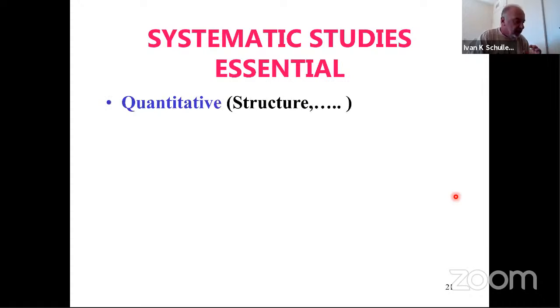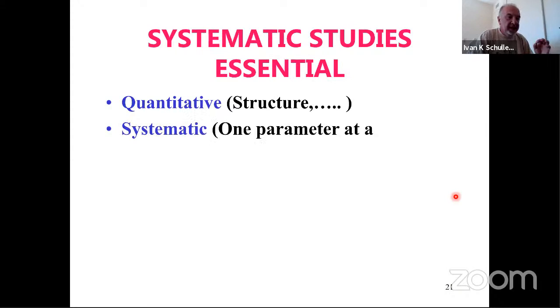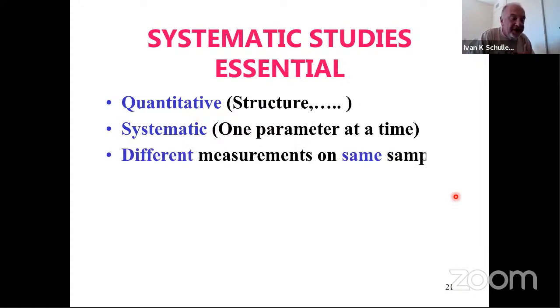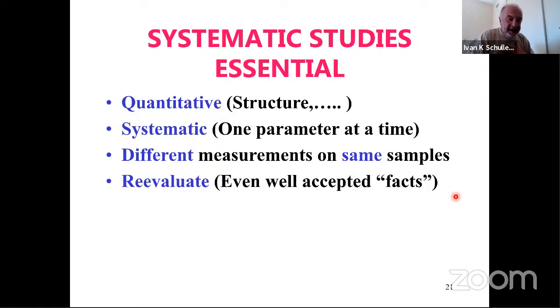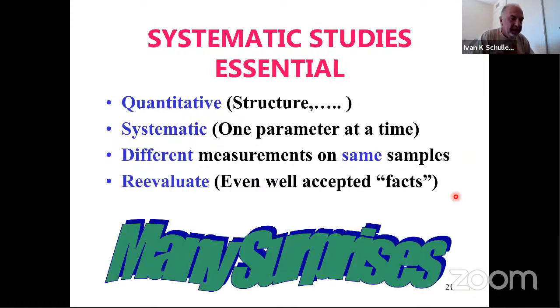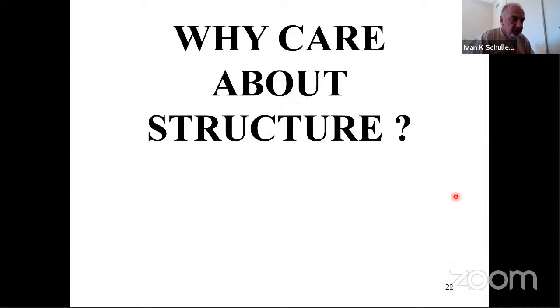And the reason you cannot do this is because systematic studies are essential. And systematic studies have to be quantitative. For instance, the structure has to be quantitatively determined. You have to vary one parameter at a time. A lot of people tend to vary too many parameters at the same time. Make different measurements on the very same samples, because this is very sample dependent, and reevaluate even the well-accepted facts. And I'm saying this for young people: do not believe everything you are told. Reevaluate well-accepted facts and make sure that you agree with them. And there are many surprises, and that's what I want to show you now here.